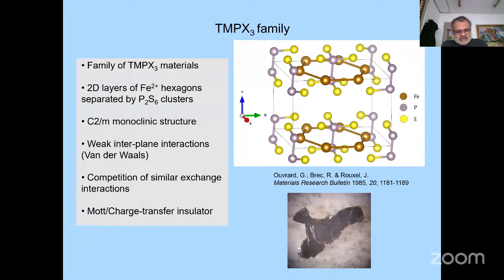So after a lot of discussion and sessions, we settled on a different family of materials. And this is a major part of the research that's ongoing in my lab right now. We selected what we know as the TMPX3 family, which is basically transition metal phosphorus X. X could be either selenium or sulfur in our case. They're organized hexagonally similar to graphite, and they have weak van der Waals interaction. And so they're often even called magnetic graphene, although there is no carbon in the system.